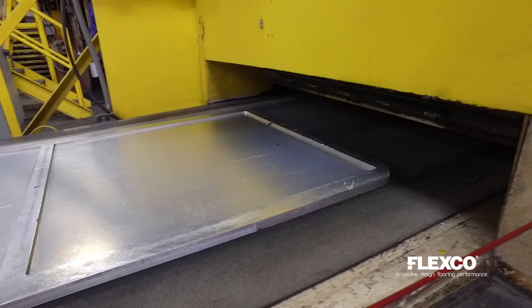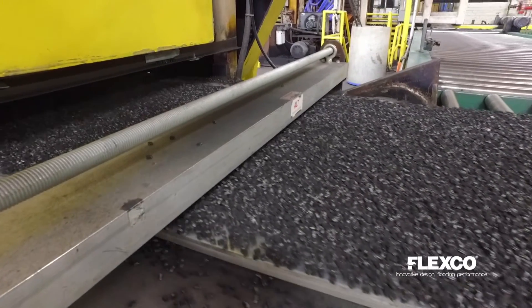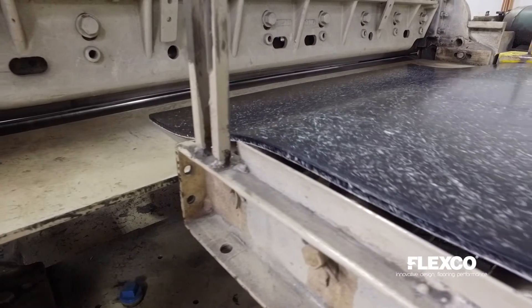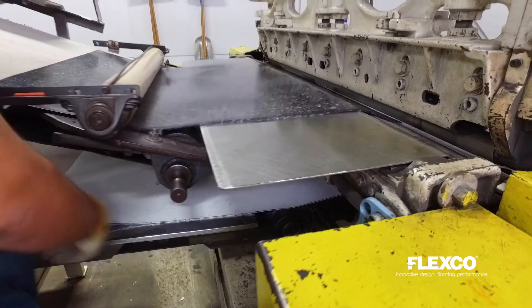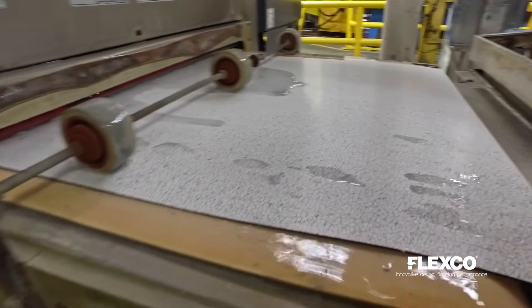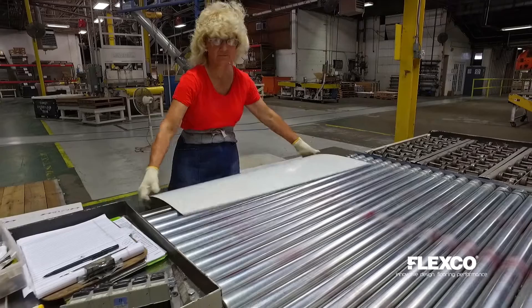ESD and conductive and solid vinyl tile are also produced in a compression molding process. Vinyl chips are carefully coated with a proprietary black conductive material and loaded onto mold boards in preparation for molding. After pressing, the tiles are cooled and trimmed. These thick slabs are then split into multiple layers according to the thickness specified. The slabs are then sanded to the precise gauge required. Next, the surface of the tiles are polished utilizing a wet sanding process. Each slab is then inspected prior to heading to the next process.